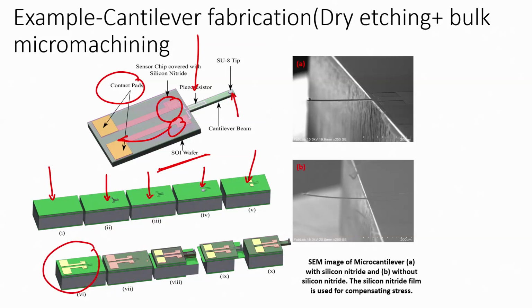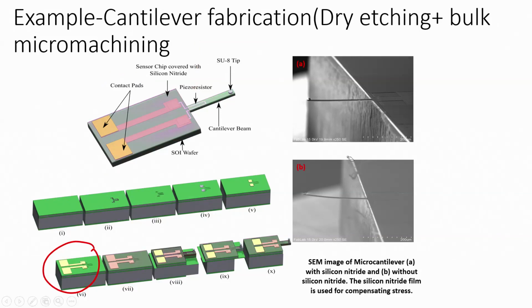After the contact pads are created, we are depositing a layer of silicon nitride. The point of depositing silicon nitride is to compensate the stress that happens in the wafer because of silicon dioxide. There is a compressive stress that comes into play because of silicon dioxide, and to compensate that compressive stress we have to use silicon nitride. If you do not use silicon nitride, you can see here that the cantilever is bent because of the stress induced by silicon dioxide.